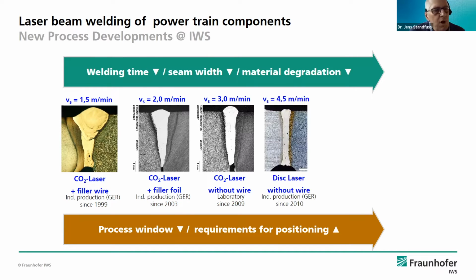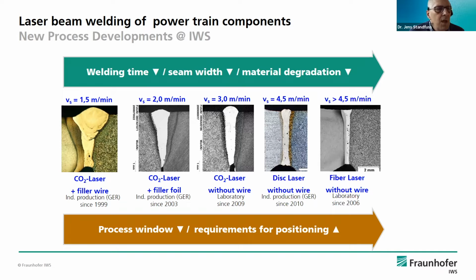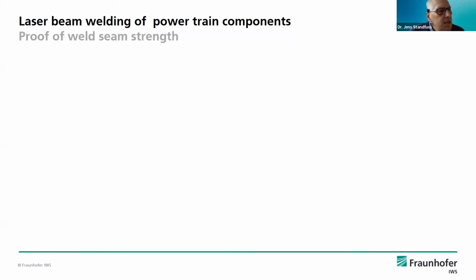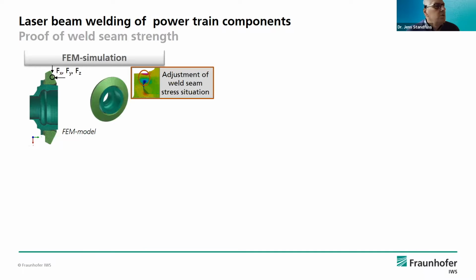processing time. And that's why with new lasers we have this chance, and we can speed up the welding speeds by a factor of 3. But the welding speed is one side. You have some requests to the product quality and how you can handle this. And our procedure is that we get a closed loop solution. Not only the process, we also give the design values to design the part and to design the weld, and you have both connected with the process. This means we can offer some special solution to adjust the weld seam to the stress situation.